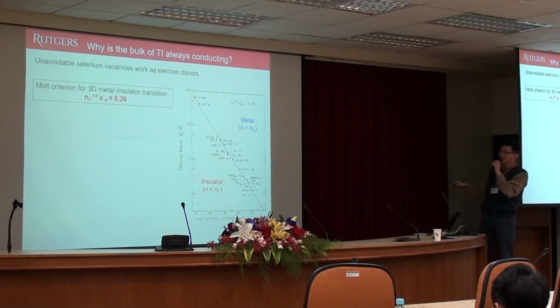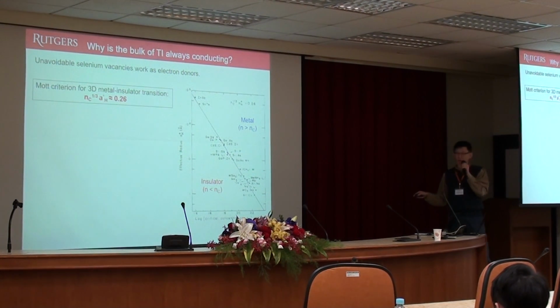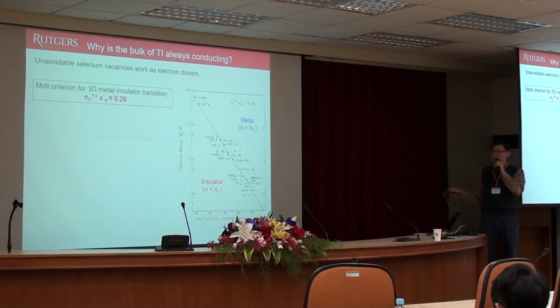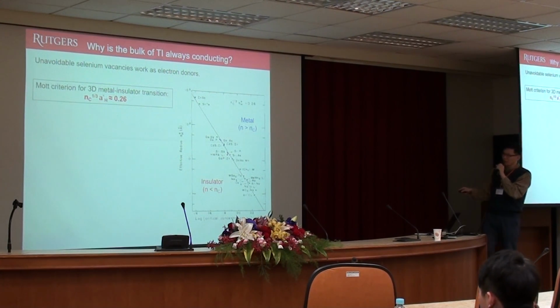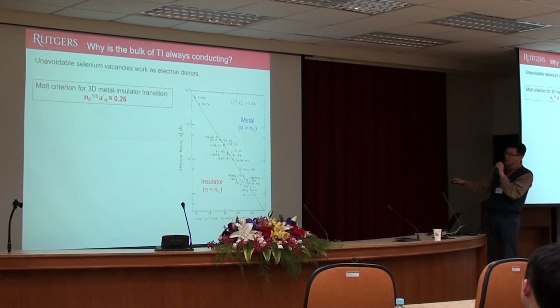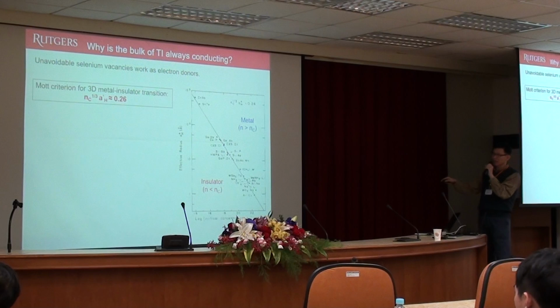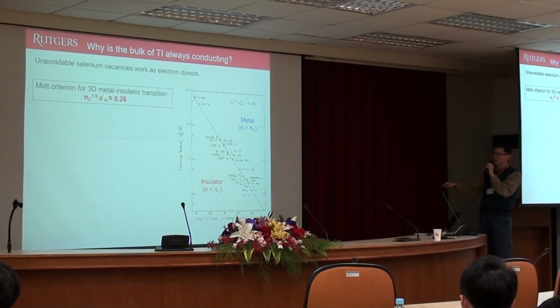For each material, you can calculate the effective Bohr radius using the effective dielectric constant and plugging in the effective mass. By plugging in those numbers, you can calculate the effective Bohr radius for all the materials, and this line comes from that. Then it turns out that, as you can see, for almost all materials, the critical carrier concentration, or doping concentration, that leads to this metal-insulator transition turns out to be quite universal.